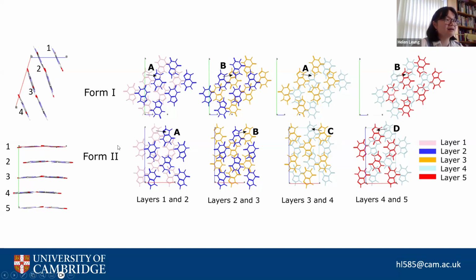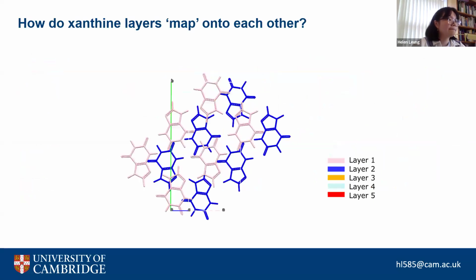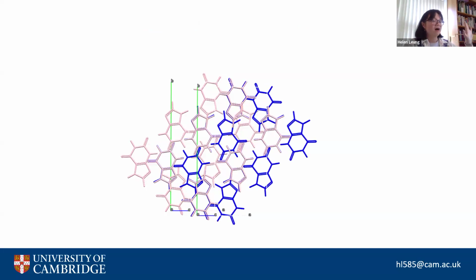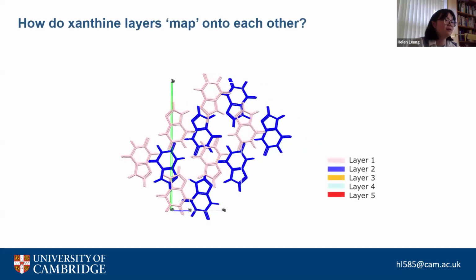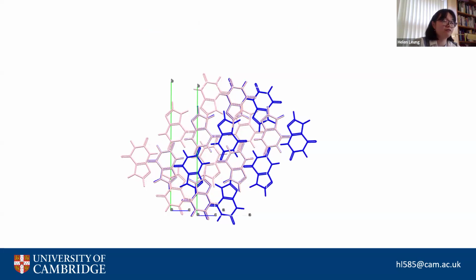And the goal was to understand how layer 1 was related to layer 2 in Form 1 versus in Form 2. So this is an example for Form 1 to show how I got to the figure from the previous slide. We took layers 1 and 2, and we wanted to understand what translation vector I have to apply to overlay layer 1 on top of layer 2. Obviously, we know that there is a depth translation, but we know that the distance between these hydrogen bonded planes remains relatively invariant. So what does the translation between the planes this way look like? Here we thought about, how do I move the pink molecules onto the blue molecules? And so you can see I've done a direct translation of the pink molecules. I'll just play that one more time. The pink molecules onto the blue molecules here. And that's how I move from layer 1 to layer 2.